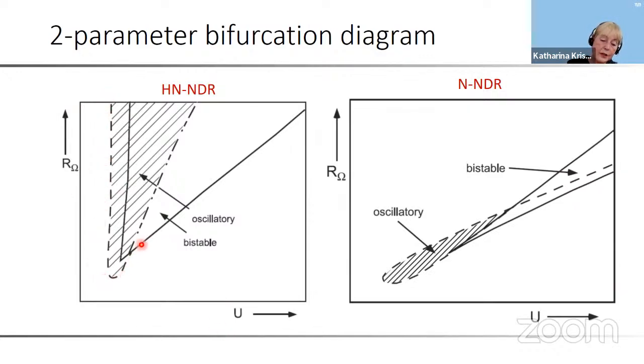And you have your oscillatory regime here, and also this opens towards large values of the external resistance. So the oscillatory range of HN-NDR oscillators is much larger than that of N-NDR oscillators. Most organic oxidation reactions of most small organic molecules like formic acid or formaldehyde oscillate due to an HN-NDR mechanism.